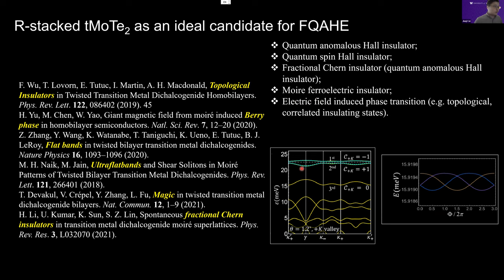I selected two of them to show the band structure of this twisted molybdenum ditelluride homobilayer. What you can see is that the top two Moiré minibands, that is the holes that sit on the Moiré superlattice, have a finite Chern number C equals minus one. Now you get the Chern band, which is relatively flat, and you have strong interaction inside the flat band. What we can do is calculate the many-body phenomena of it. Basically, you can construct a relatively small lattice size and see how those electrons interact with each other and form some